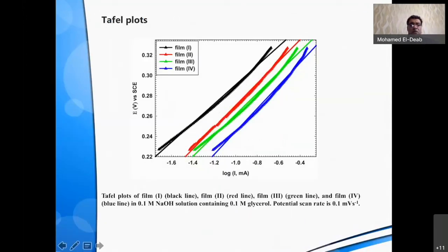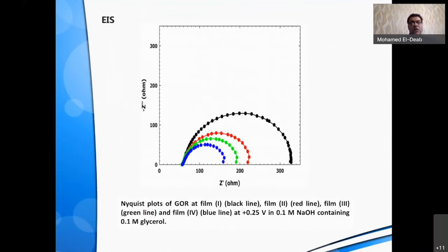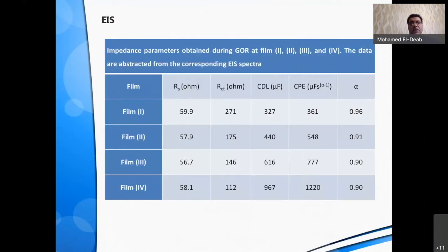Also, we measured Tafel plots. So also this, the blue one, which is film number 4, prepared in presence of bromide, shows the highest current, and more or less the Tafel slopes are the same. So no significant change in the rate determining step for glycerol electrooxidation. And here also this is electrochemical impedance spectroscopic measurement, and we also found the RCT for film number 4 is the smallest, which indicates also that charge transfer is much supported at this electrode. As you can see here, we have a charge transfer resistance of 112, which is much less than the unmodified or the blank film, which is prepared in absence of any additive.